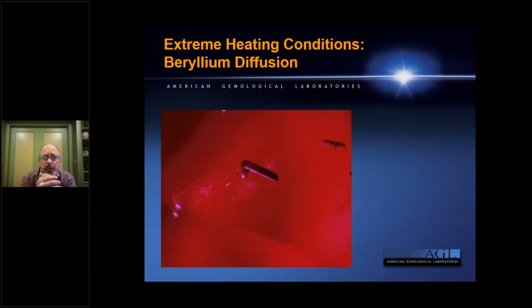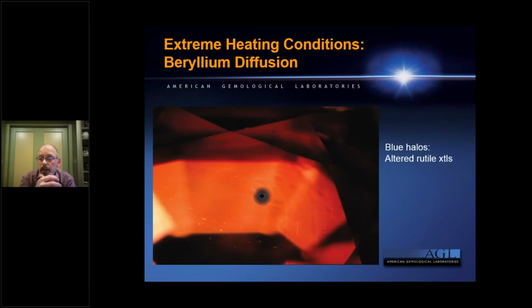Some of the inclusion features that you may encounter: one of the sources that they commonly treat with for beryllium diffusion is a deposit known as Songea in Tanzania. This source commonly has crystals of rutile, so titanium oxide. After heating for beryllium diffusion, you see that there are actually halos of blue color which will surround these kinds of stones.